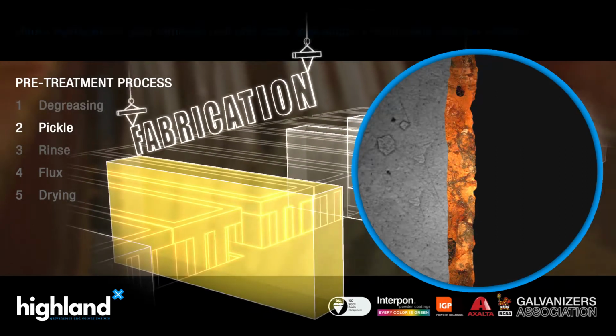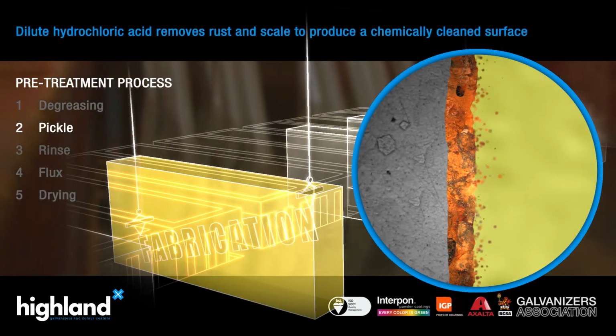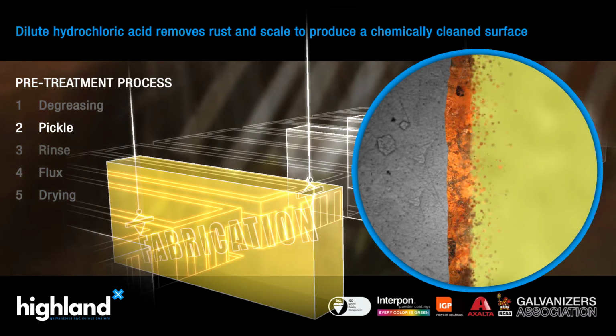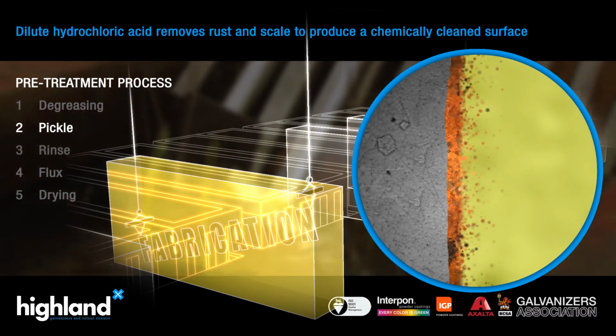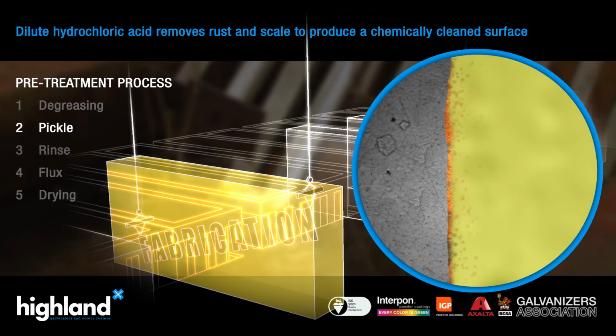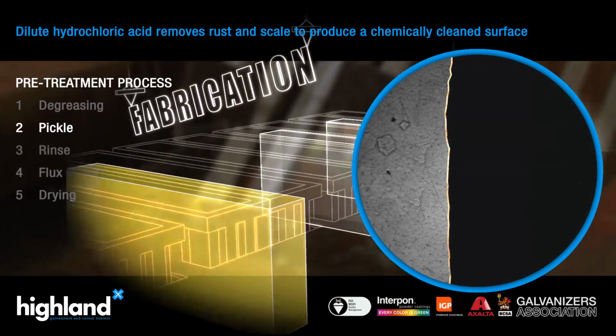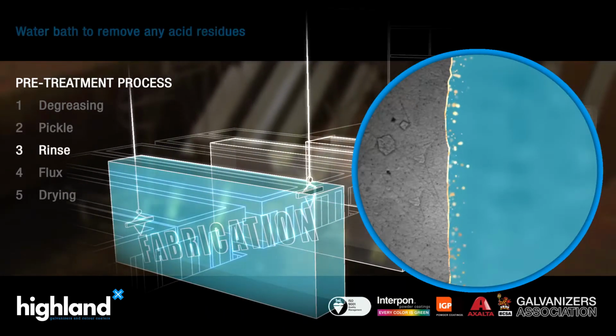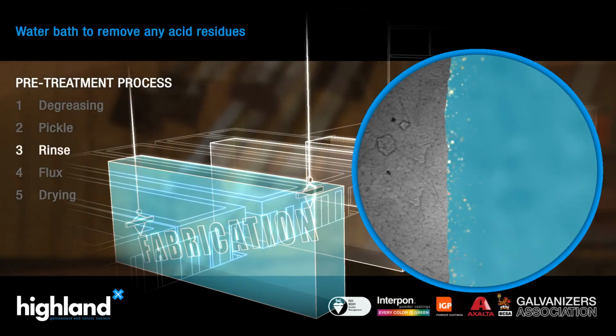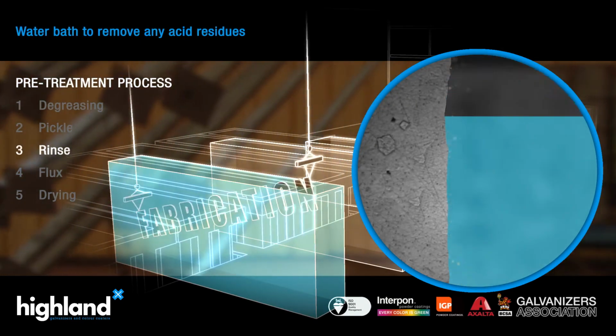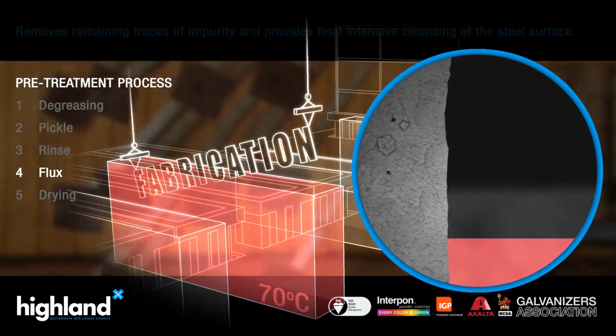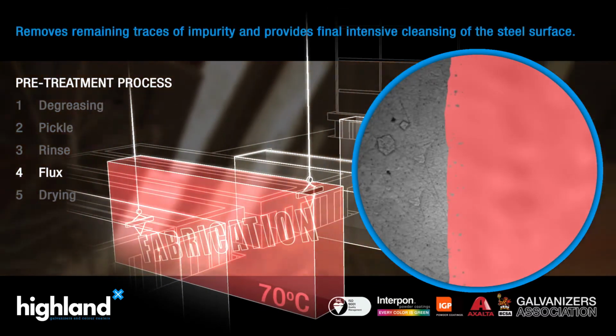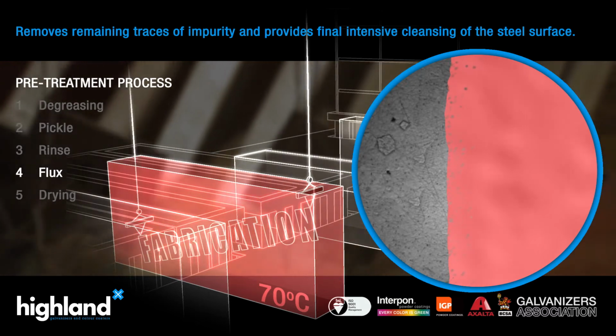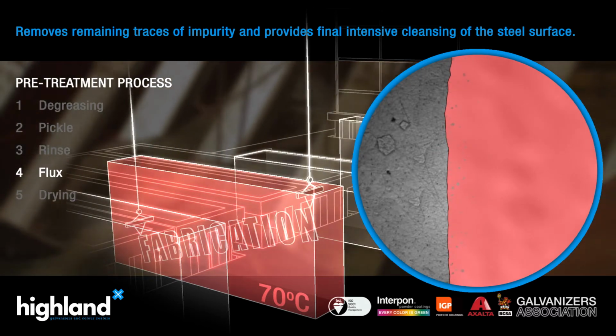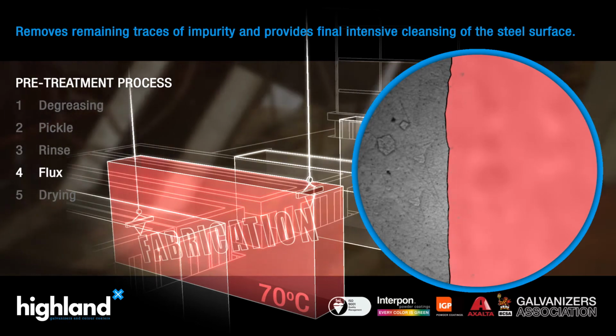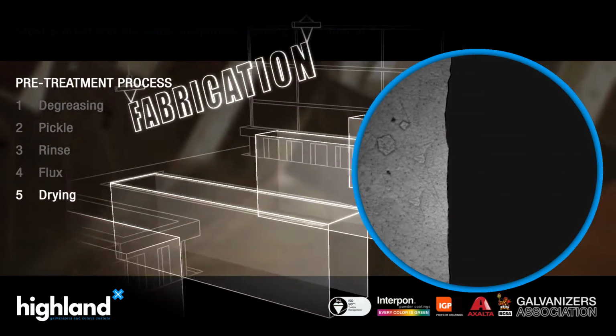It is then pickled in a dilute hydrochloric acid which removes any rust or scale. This process on average takes 1 to 2 hours, but can take longer if the steel has a heavy layer of rust. It is then rinsed to remove acid residues before being dipped in a flux solution which is heated to 70 degrees Celsius. This fluxing leaves dissolved salts on the surface of the metal, which helps to wet the steel components with zinc, improving the quality of the coating.